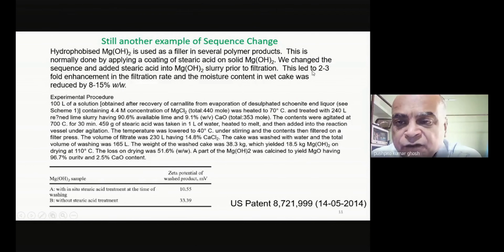Effectively, we were able to increase the filtration rate by almost a factor of 3, and we were also able to reduce the moisture content by 15%. So it was a huge benefit, and merely by changing the sequence. Why only make the pure product and then coat it with stearic acid? Why not try to incorporate the stearic acid at the time of filtration to gain an extra advantage?